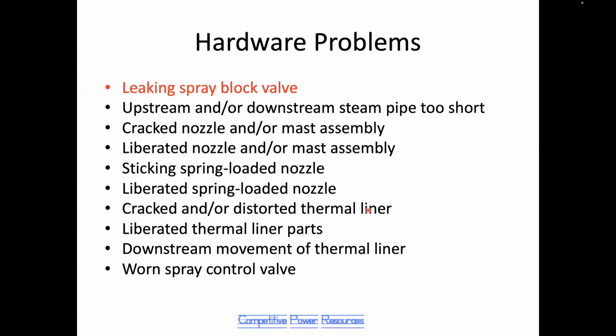Thermal liners are often installed inside the attemperator steam pipe to prevent water contact with the pipe itself. Those liners can become distorted or cracked if water impinges on them. If the liner starts cracking, parts of that liner can go downstream. Sometimes the entire liner will break loose and move downstream. And a worn spray control valve will also negatively impact the quality of the spray.